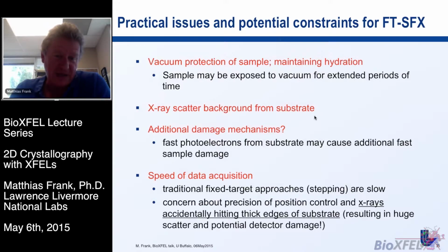There could be additional damage, and I haven't really talked about damage much other than saying that X-rays are potentially damaging your sample. Well, it turns out for fixed targets, because you not only have your sample in the X-ray beam, you also have the thin membrane or the substrate in the X-ray beam. Fast photoelectrons produced in that substrate may cause additional damage. So the damage may actually appear faster than in, let's say, a liquid jet. And then there's always the issue that with fixed targets, the data acquisition tends to be slow, in particular if you are stepping your sample through. You basically move your sample, you stop, you shoot at it, you move, stop, shoot at it. It's a relatively slow process.